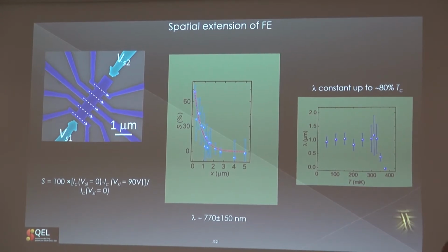So if you think of some heating effect, of course, this completely rules out any heating, because heating in superconductors, and here there are people working with qubits, many people working with qubits, so they know very well it's a very complicated problem. When you are at sufficiently low temperature, the presence of the gap in a superconductor basically weakens drastically the electron-phonon interaction in the system.